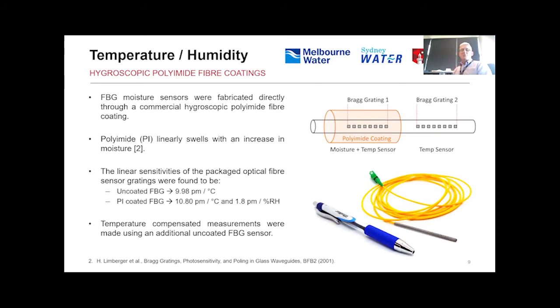In this case, a transducer based on polyimide coating. Polyimide is hygroscopic, so it will actually swell in a linear fashion with respect to humidity, and it's reversible. So the act of that polyimide coating swelling with humidity causes the period of the Bragg grating to change. The spectral features I showed in the previous viewgraph will actually move as a function of humidity, and we can calibrate against that and actually have a real-time sensor.